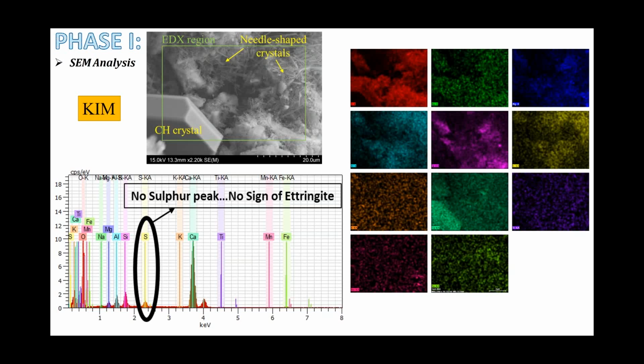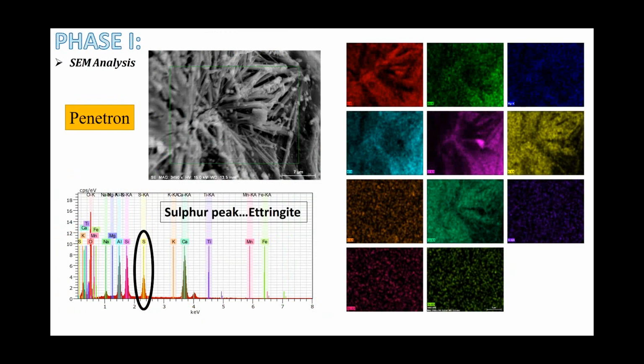Penetron is another product that I've used in my research. This also shows crystal growth inside. I tried to examine it using the X-ray analysis, and it turned out differently, because this product seems to be inducing ettringite, which, when you compare it with the other product, is not a good thing for the concrete. So we need to be cautious whenever we are using this type of crystalline admixture. As you can see here, there's a peak for sulfur, which indicates ettringite inside.